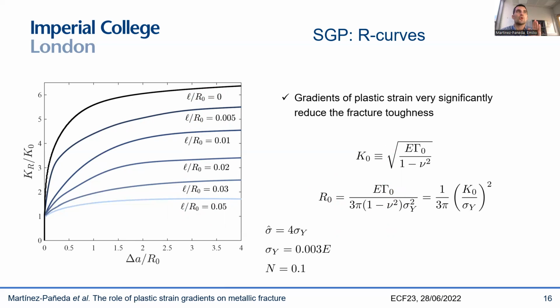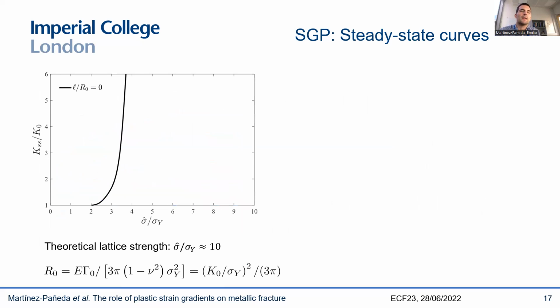So what we do next is compute the steady state toughness curve. You see that these crack-growth curves all plateau at some point. So we're going to run them until we get to this plateau level, and this we're going to call the steady state fracture toughness. And we're going to compute that for different levels of the cohesive strength, because this cohesive strength you can relate to that atomistic decohesion strength that I discussed before, right? Now we're taking 4 times the yield stress, otherwise we wouldn't see anything with conventional plasticity, but we're going to change that number and see if we can get close to the cleavage strength. And this is what you see here.